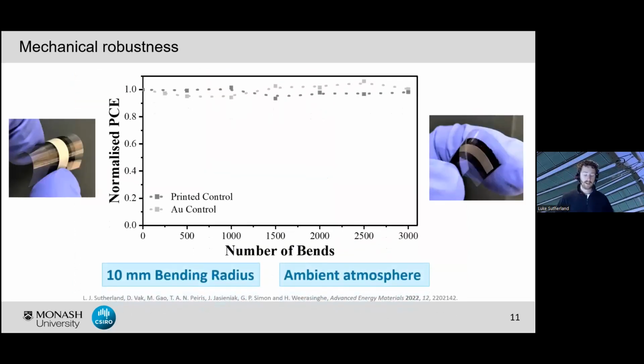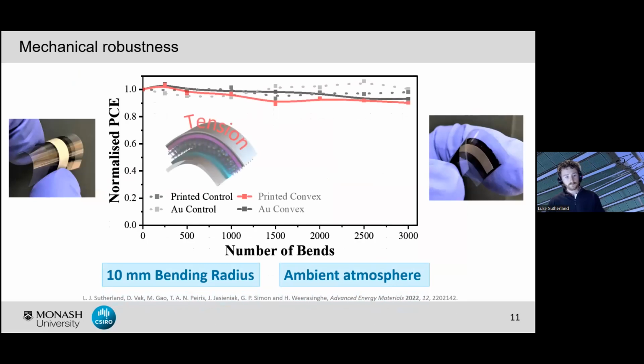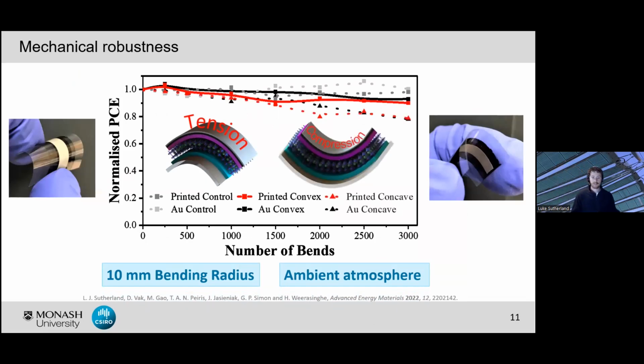And so we set a 10 mm bending radius. This is just in the ambient lab, no encapsulation. And for devices placed under convex bending, so this is with our top electrode in tension there, we see minimal degradation after 3,000 bending cycles. Once we put our devices under concave bending, we do see slightly more degradation under this regime.